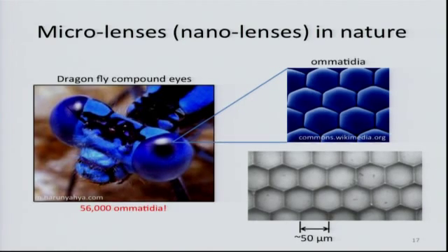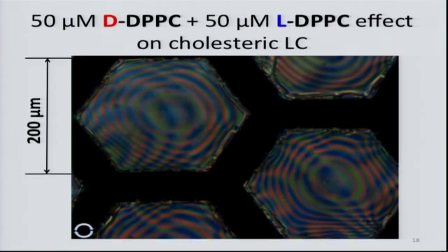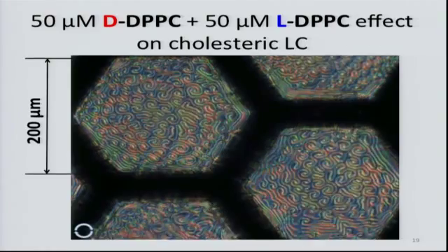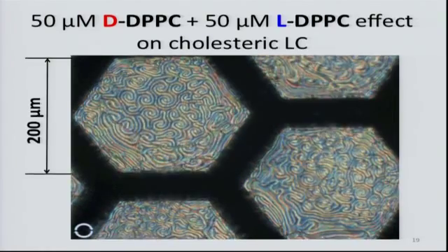But now I would like to return to the liquid crystal sensing of chiral molecules. So again, cholesteric films underwater typically look like this. They haven't relaxed yet, so these rings are not looking very good, but this is what they look like typically. And after the addition of phospholipids in the water, the following typically happens. So this fingerprint texture appears. And these fingerprint textures are like signatures of different surface active materials.